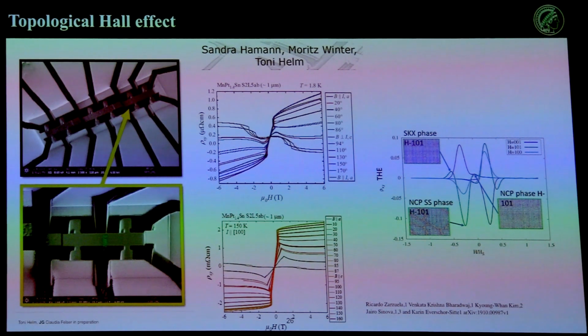So this here is just the simulations. We take a magnetic field and rotate it in our sample, and we can actually see it. So here is the skyrmion state. Here's this spin spiral state that's non-coplanar, and here's this non-coplanar state, which is just everything's non-coplanar. And one thing you already see is that the skyrmion state does not match this exact point, because it's the higher field case, but the skyrmion state has a much lower topological Hall effect than the non-coplanar texture or the spin spiral texture, which seems to be the case for almost all skyrmion systems.